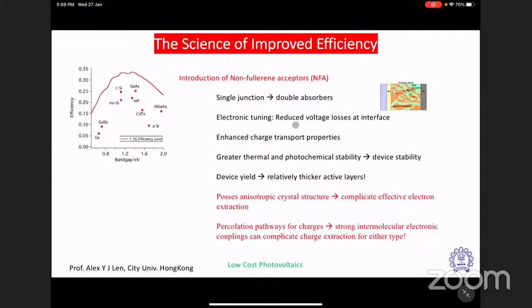And right electronic tuning between the LUMO offsets can introduce reduced voltage losses. And we will see how the charge transport properties get enhanced. At the same time, a byproduct is great thermal and photochemical stability, which makes the device stable. And because the transport properties got better, I can go for thicker devices.